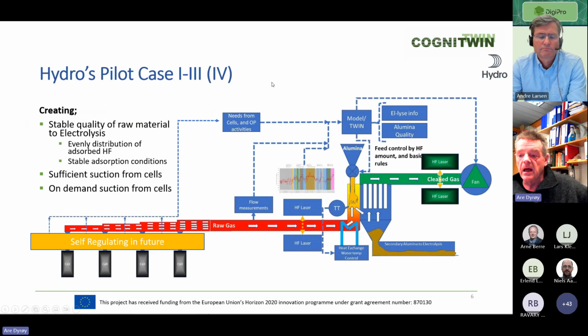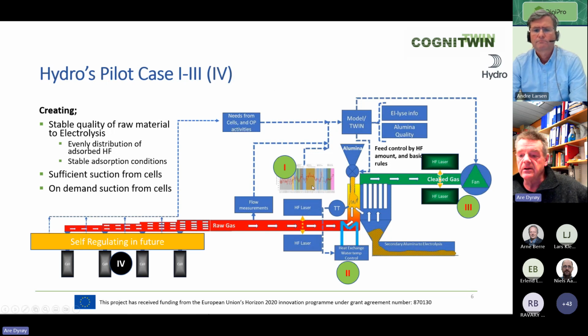In Hydro, we built it up by 4 cases in the beginning, where we have, first of all, meeting the necessary primary alumina feed to the reactor in order to have a flat and a constant fluoride part of the alumina. The second was to keep the reactor temperature within the best area of absorption of HF. Third one was to regulate the main fans, both to have full control on the gas flow as such, but also to save energy. We also had a fourth